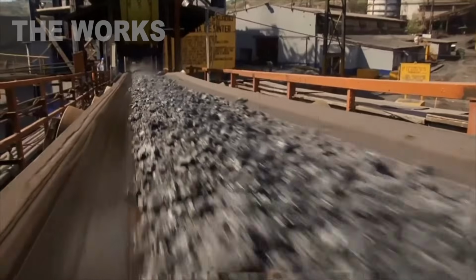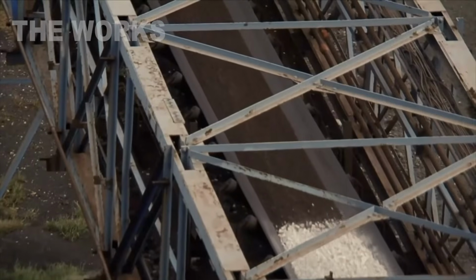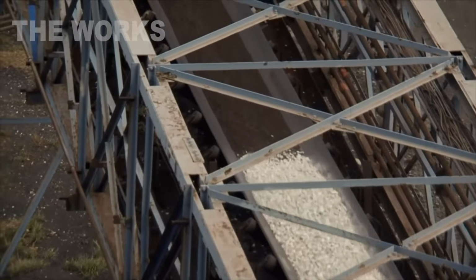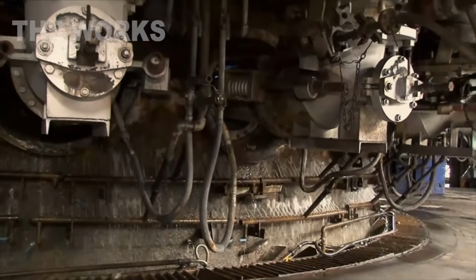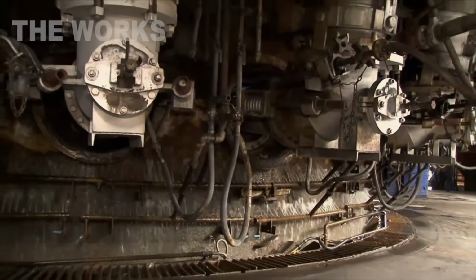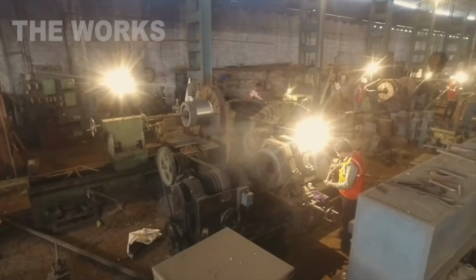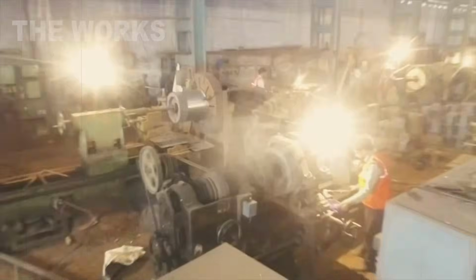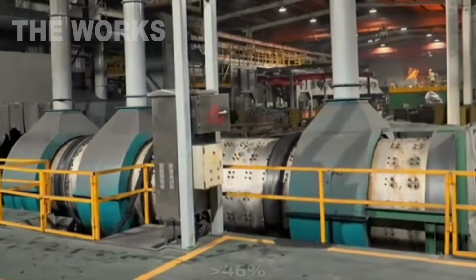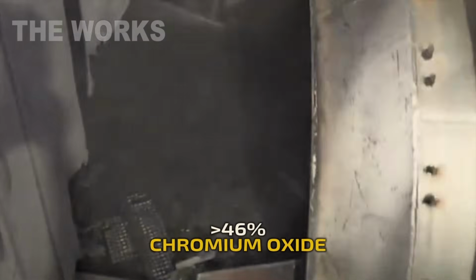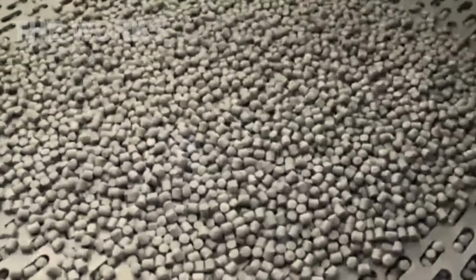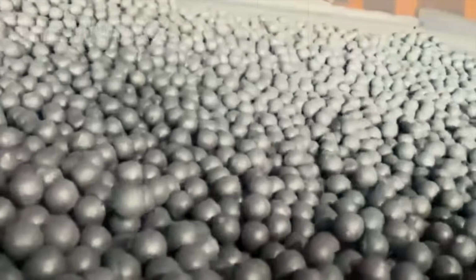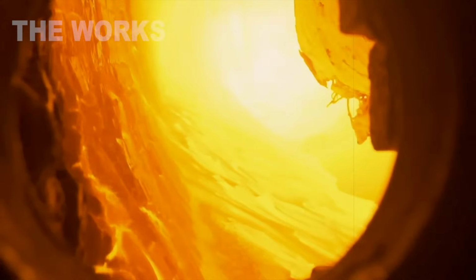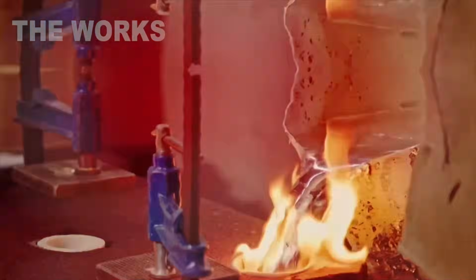Magnetic separation is also used. Chromite is weakly magnetic, but modern high-intensity magnetic separators can attract it and separate it from non-magnetic impurities. After enrichment, they obtain chromite concentrate containing 46% or more chromium oxide. This is ready-made raw material for metallurgy. The concentrate is dewatered, dried, and sent to ferroalloy plants. Lump ore is needed for ferrochrome production. Fine powder doesn't melt well in the furnace.